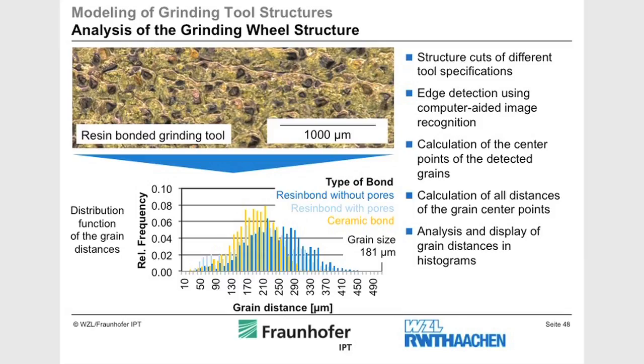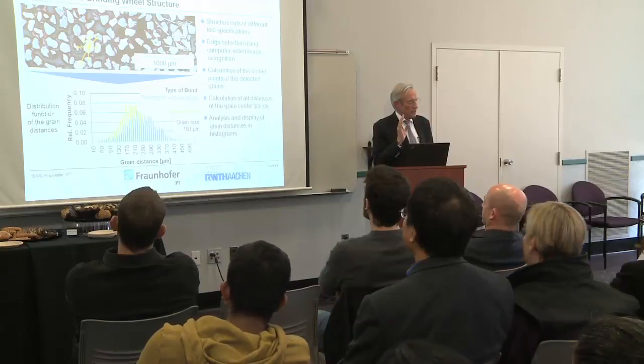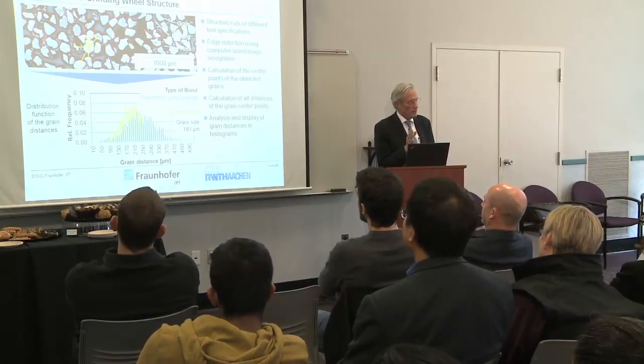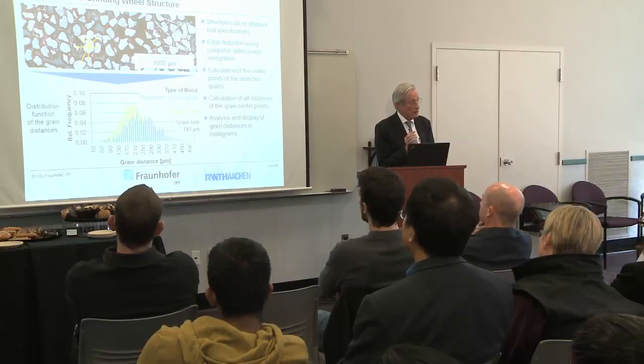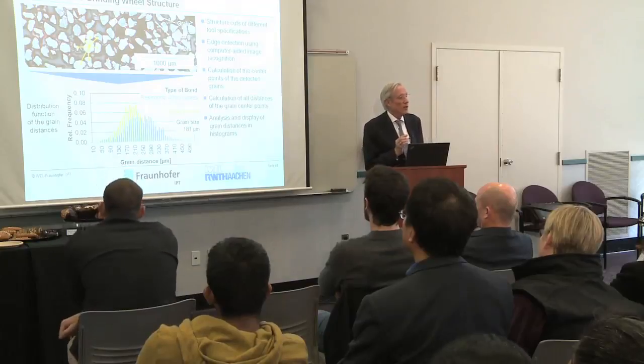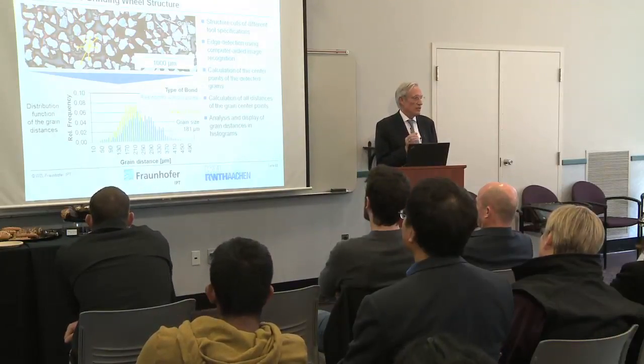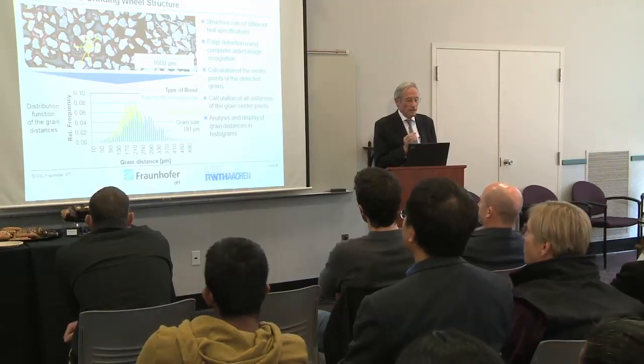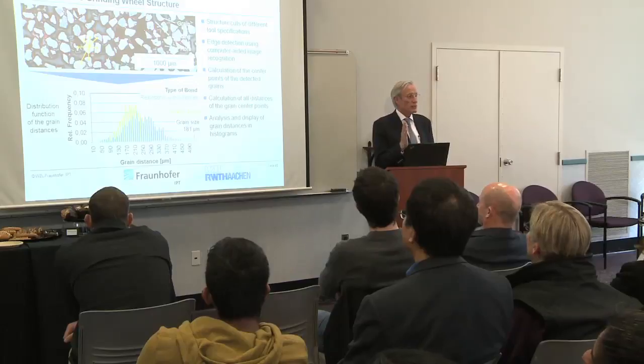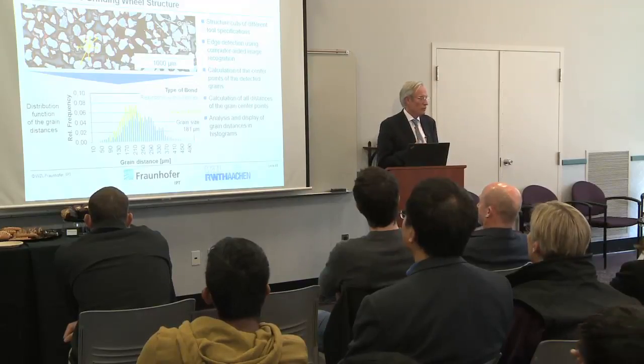So that is a real grinding wheel. It's a resin bonded grinding wheel. You just look at it. You see the grains. You see the bonding, and now we did some measurements to really see the real distribution of these grains. And what we found out was, we made grinding wheels with the same concentration of grains. So the volumetric concentration of grain was exactly the same. It was 24%, C100 or V240, so 24% was the grain concentration. The grain size was also the same. The geometry was the same. The only thing that was different was the bonding.